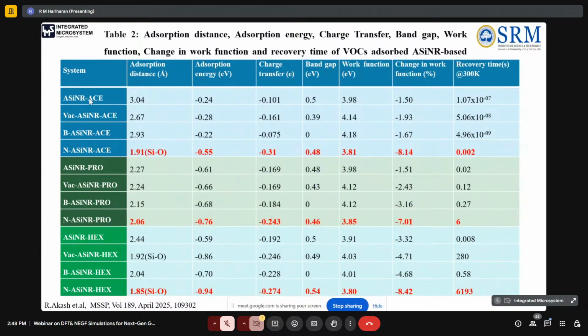In the first case, the blue box resembles acetone, the green box resembles propanol, and the light green represents the hexanol biomarker. If we see very clearly in each of the boxes, for acetone, the nitrogen-doped silicene nanoribbon has a strong attraction towards the acetone biomarker. The adsorption energy is the least here. So one can say the nitrogen-doped system shows very good adsorption properties, which is confirmed through the charge transfer as well as the change in the work function percentage. The adsorption energy is correlated with the charge transfer as well as the change in the work function.